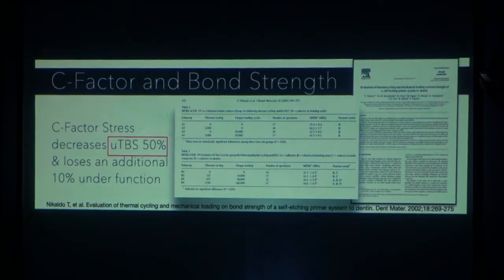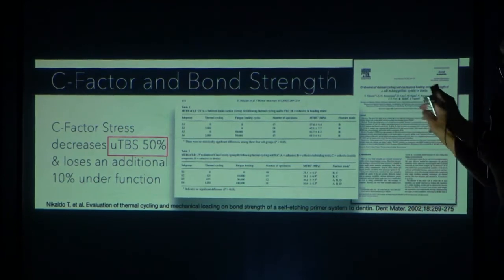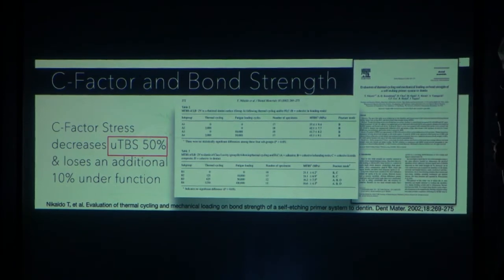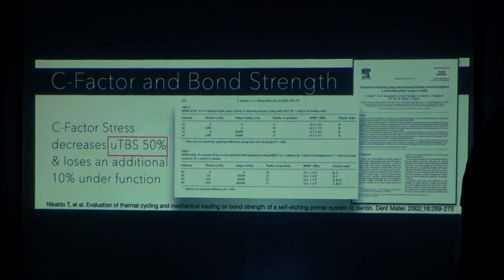So the preps, what do they look like? You've been through that slide. This paper had both the testing of C factor, and after it tested the C factor, it put the restorations under function, and it found out that if you don't control for C factor, you lose 50% of your bond strength. In other words, you're not going to 40 or 50, you're going to start with 20. But they found out these lower bond strengths, they could seal the tooth, but when they put them in the chewing machine, then they started to see a fatiguing and a loss of another 10% of bond strength. And the deduction is that over time, you will lose all of your bond strength and you can have a failed restoration.